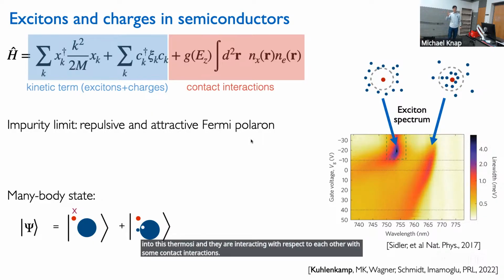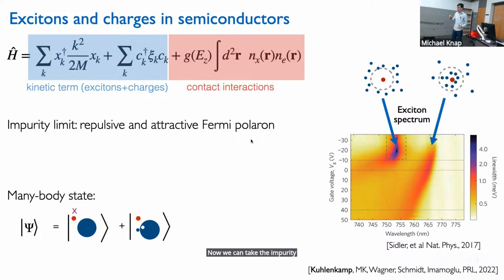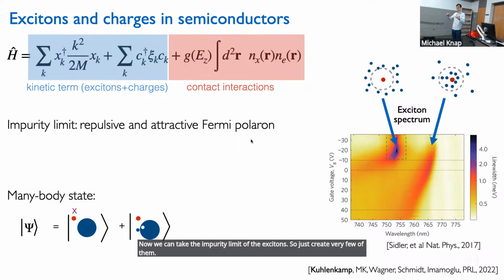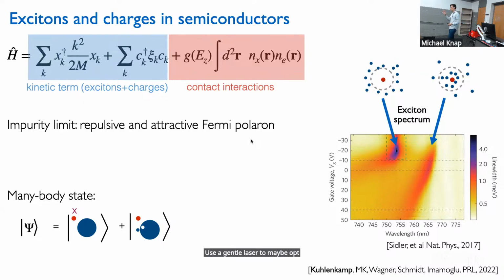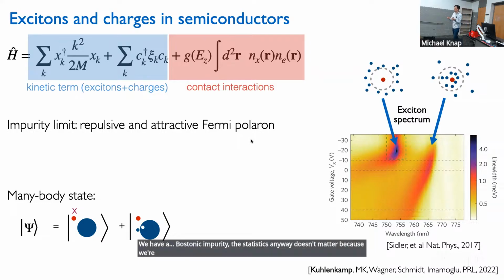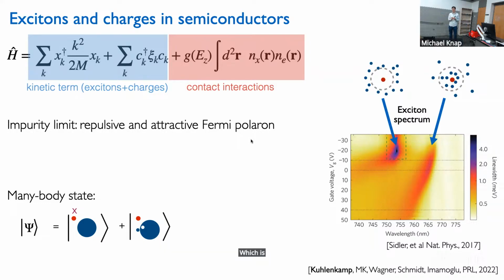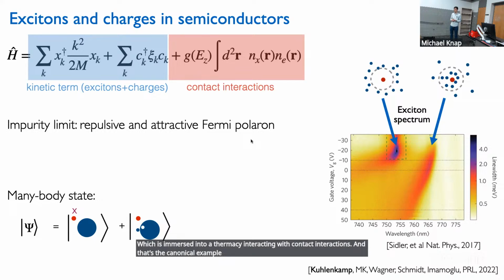Now we can take the impurity limit of the excitons. So just create very few of them. Use a gentle laser to maybe optically excite only a few of these excitons. Then we have a problem which we see often in cold atom settings, actually. We have a bosonic impurity. The statistics anyway doesn't matter because we're considering the impurity limit, which is immersed into a Fermi sea, interacting with contact interactions. And that's the canonical, well-studied example of a Fermi polaron.